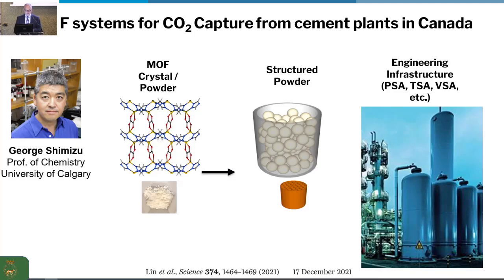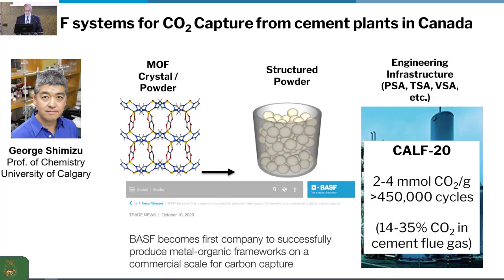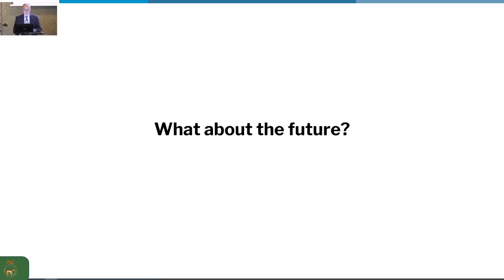And BASF is making hundreds of tons of this MOF and supplying at least 3 plants in Canada that deploy this technology. And here, as of publication of this work back in, I think, 2021, this material has cycled over 450,000 cycles. And that's because of the strong bonds that I've been talking about. That's because of the permanent porosity, that things don't collapse as you cycle gases in and out. They remain open. So this is a big commercial success. What about the future?